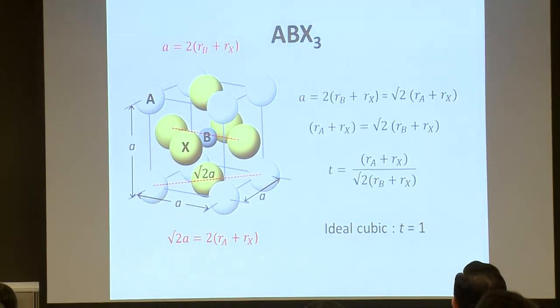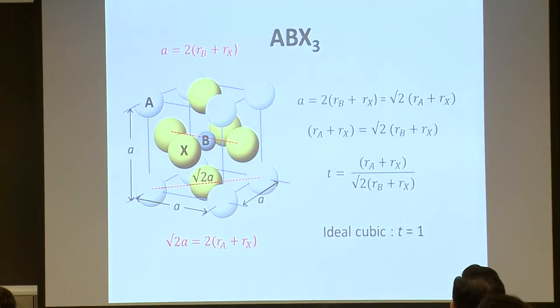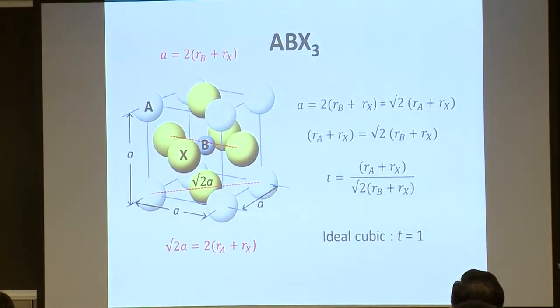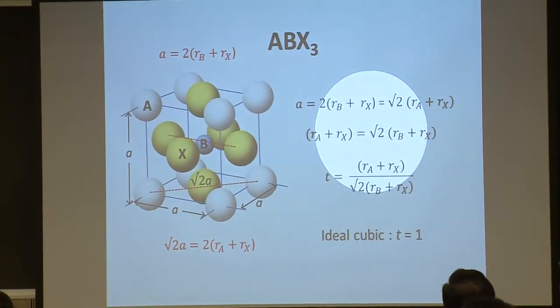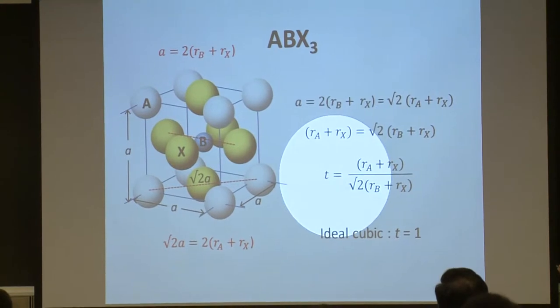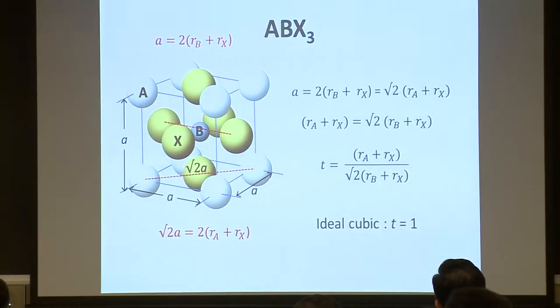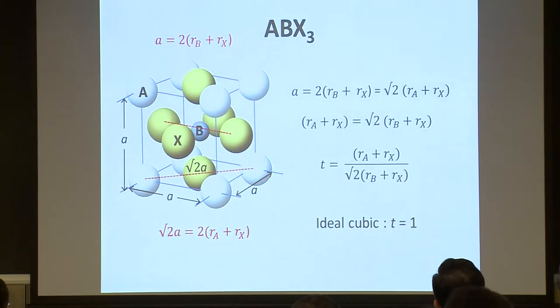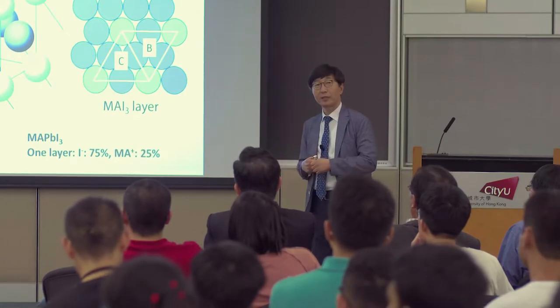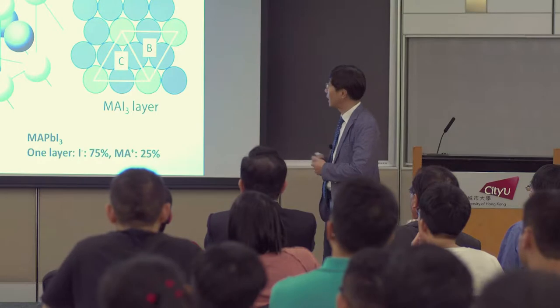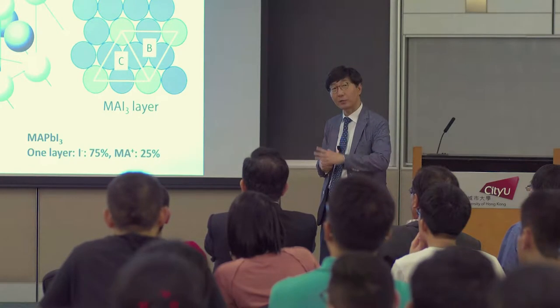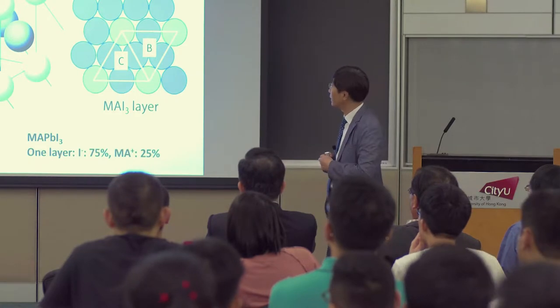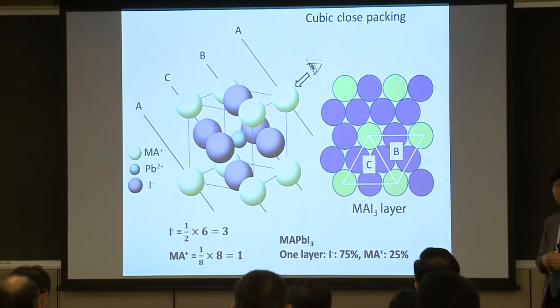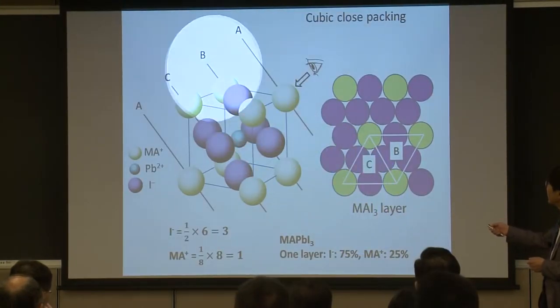If you calculate the radius with the radii of A, B, and X, then you have this kind of relationship, and for the cubic structure, the tolerance factor becomes 1. If the tolerance factor is between 0.8 and 1, then you expect the formability of the perovskite structure. If you look at the close packing model, which assumes all the sphere elements are the same element, then the perovskite looks like a cubic close packing structure, meaning an A, B, C sequence, A, B, C sequence.